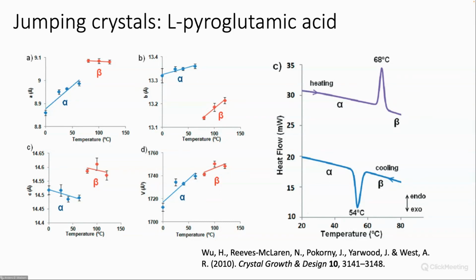It could also be induced by other things than temperature, for example by light, but in this case we're looking at L-pyroglutamic acid, and this system, as shown here by Wu and company, has some rather abrupt changes in unit cell dimensions as we heat the system somewhat above room temperature. And there's a certain hysteresis of this phase transformation between these alpha and beta forms, and both of these transformations are related to a jumping phenomenon.